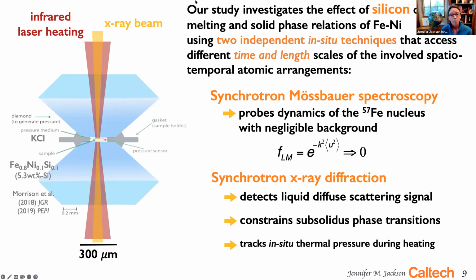And so our approach is a dual technique approach that investigates an iron nickel silicon alloy. So we're investigating the effect of silicon on the melting phase relations of an iron nickel alloy using two independent in situ techniques that access different time and length scales of the involved spatiotemporal atomic arrangements. And that is, we are using synchrotron Mössbauer spectroscopy, which probes the dynamics of the iron-57 nuclei with negligible background. And synchrotron X-ray diffraction detects liquid diffuse scattering signals, constrains the subsolidus phase relations, and tracks in situ thermal pressure during heating.